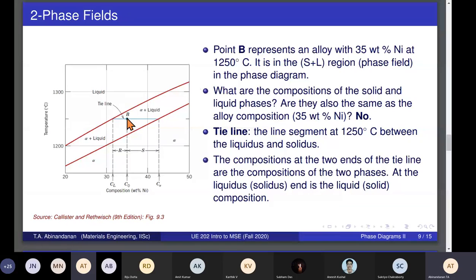And this again has a solid thermodynamic basis, which we will try to give a hint of later in the next presentation. But the mechanics of this calculation works in the following way. So what you do then is at 1250, you draw something called a tie line. And the tie line is basically the line segment at 1250, right from the liquidus to the solidus curve. So it is this line segment which is called the tie line, and the ends of the tie line then give you the compositions of the two phases. The liquidus end of the tie line gives you the composition of the liquid. The solidus end of this tie line gives you the solid composition.